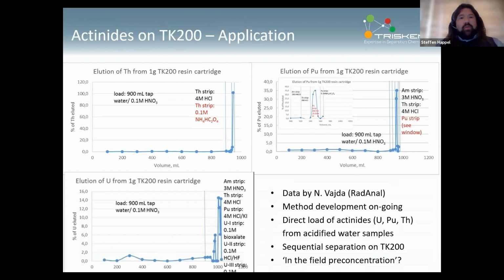That pretty much boils down to an application that we feel is quite interesting. So that's really ongoing work that still needs to be optimized. But the idea is take a water sample, acidify, load through cartridge at a bit elevated flow rates, concentrate the actinides on the cartridge. In that case, it's probably going to boil down to uranium, thorium, and plutonium. Americium is retained to a certain extent, but we feel for 1 liter, it's not good enough. That might work for smaller volumes at the end of the day. Then just step for step elute the